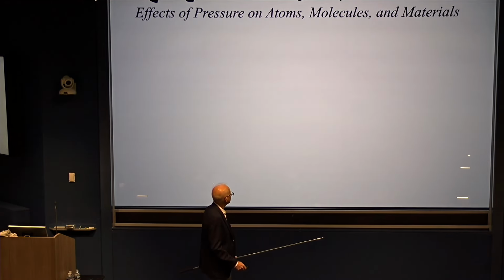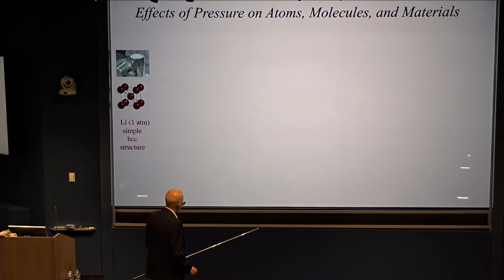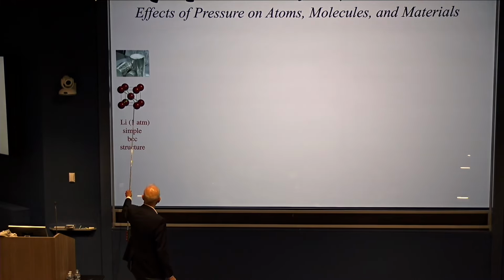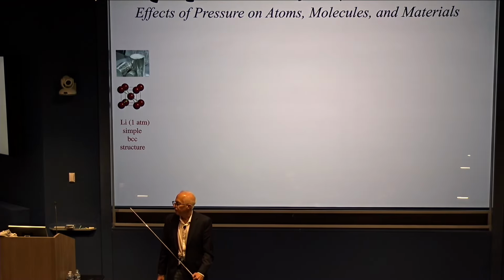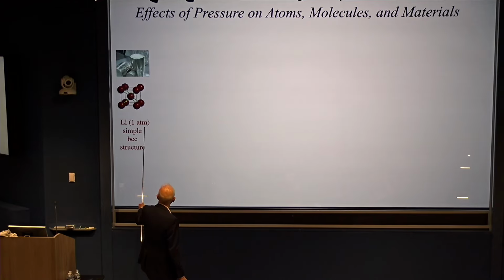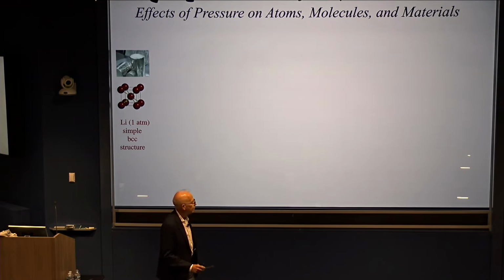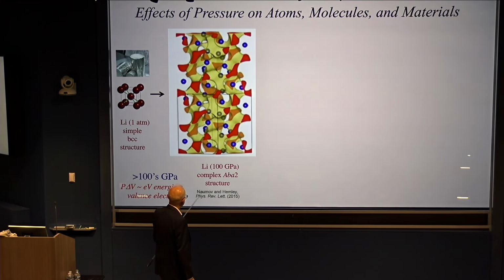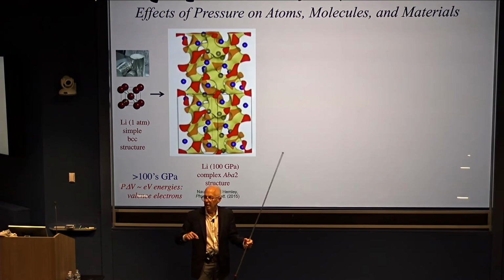times tonight. So another important point I want to make is, if you just take a simple system, and an example of this interesting chemistry, you take a textbook free electron metal like lithium or sodium. Here we have this nice BCC structure. It's a nice shiny metal. It's what we built our modern theory of metals in terms of quantum mechanics on. And if you compress it to, say, a megabar of pressure, 100 GPa, something quite dramatic happens. The electrons don't stay in the conduction band. They don't do what I showed in that simple model. They actually take on some very different character, and they condense into pockets and other places in the structure.